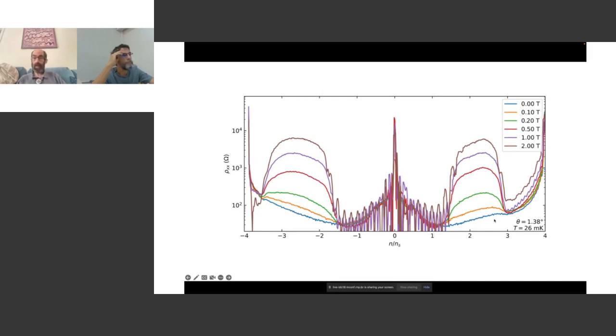So if you look in here, there's a lot of fast oscillations. If we look as a function of magnetic field, you see that there are wiggles, and these may be familiar to some of you. These look like Shubnikov-de Haas oscillations where we're filling and emptying Landau levels. But there's something funny, which is that each dip that should appear seems to be doubled. There's also this magnetoresistance that I mentioned.